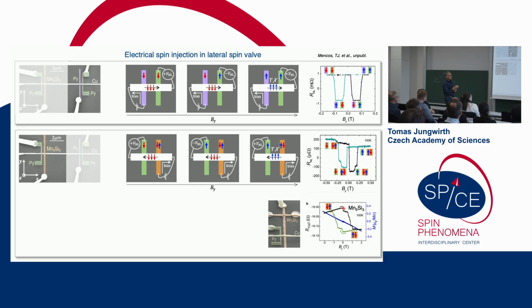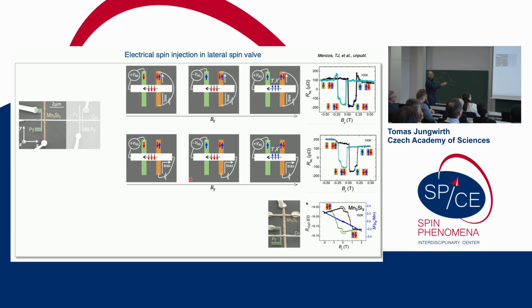So very good. This was the experiment, which was completely analogous to the experiment with the ferromagnetic electrode. But now let's try the other one. Now let's try to bias the manganese 5 silicon 3 in this geometry, where you actually apply the bias just along the injection electrode. In ferromagnets, this does not lead to a spin signal. But when you look experimentally into manganese 5 silicon 3, you see that there is a signal, and the signal is actually analogous to the signal which you get in this ordinary biasing geometry. So that's very unconventional. People have not observed this with ferromagnetic injectors.